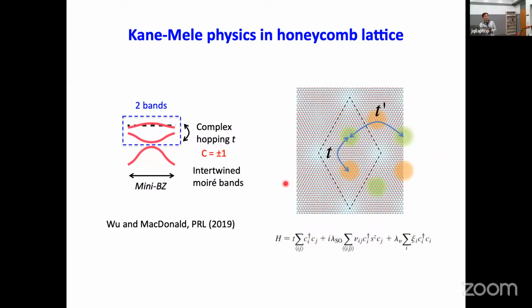In that case, you can think of the gap opened here as the hybridization gap that is created by the Moiré potential, and that has to be large compared to the folded band without that correction. Then the bands can be made really flat, if you know what I mean.